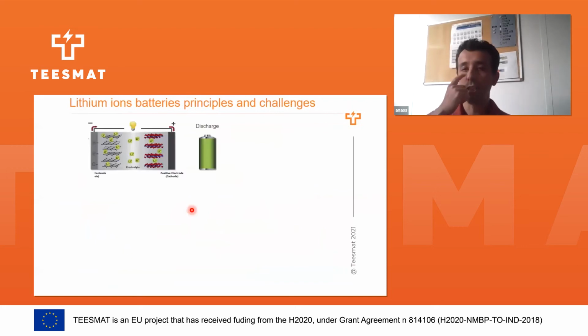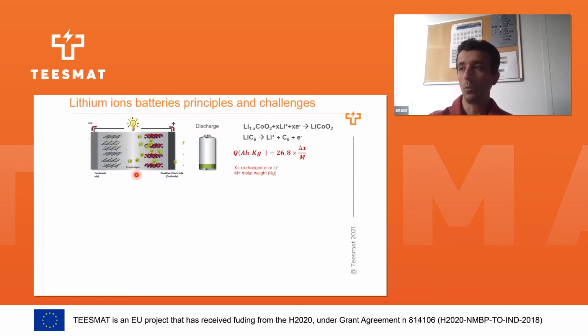So after this overview, I will briefly introduce lithium-ion batteries. This is the way it works. In general, we have a negative electrode, which mainly consists of graphite, and a positive electrode, in this case lithium cobalt oxide. During the charge, we oxidize lithium and remove it from the positive electrode material, and in the meantime we form a passivation layer at the electrolyte. This electrochemical reaction follows these chemical reactions: at the cathode we have a reduction, and at the anode we have the oxidation of lithium. And the capacity that is exchanged during this process can be calculated and linked